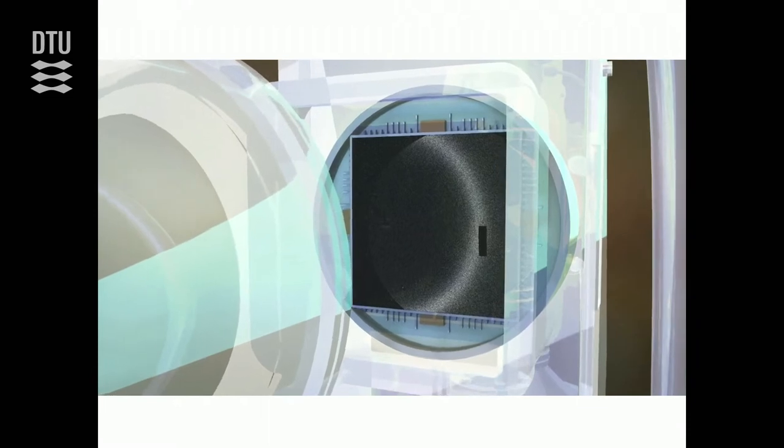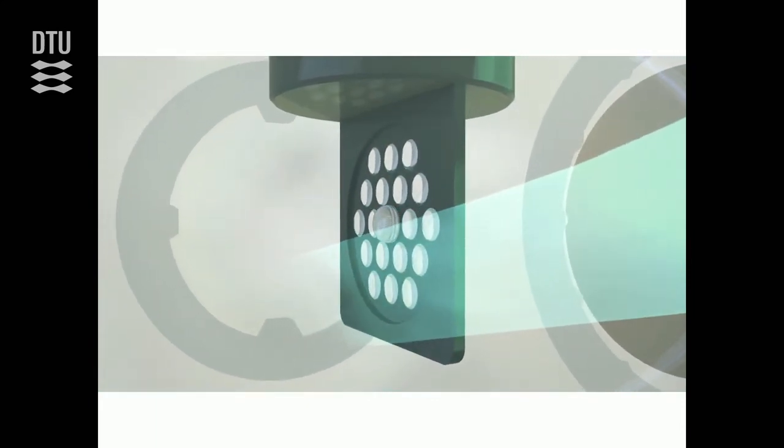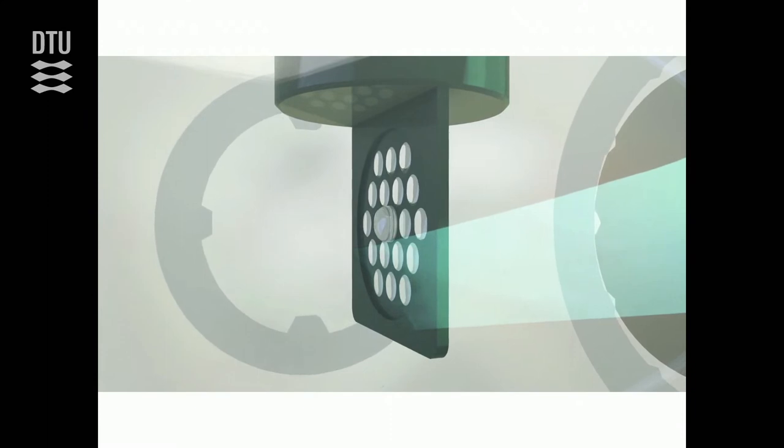As you can see, here is a ring. And this is an indication of the structure of the liquid. The distance from the radius out to this ring gives you, in this reciprocal space, which phase we are in. And this is clearly a high-density liquid phase, or actually high-density amorphous ice, if you haven't heated it yet. The question is, what is going to happen now? As we first come in with this infrared laser, the sample will start to expand, as you can see here, as we heat it up.